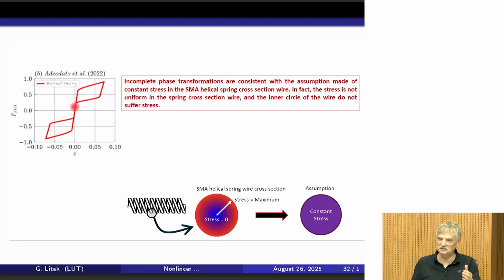But there is some change of temperature also happening. However, you needn't increase the temperature to reach the critical value, because the critical temperature is defined for the sample with no stress. If you provide some stress, then the temperature also changes. So you are right, but there are three components.